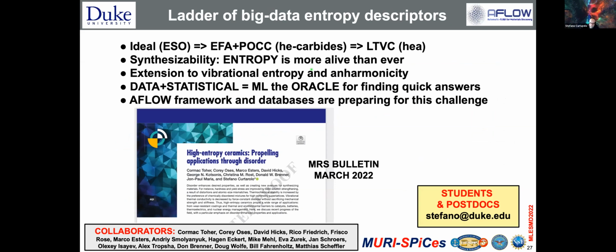Anyway, let me summarize. Disordered systems. We have embraced disordered systems since several years ago because we believe that disorder is unavoidable. We want more things, so disorder is going to kick in. To understand synthesizability when this disorder kicks in, it's all about entropy, because entropy gives you the latent heat. And the latent heat is important for nucleation. And you will find also, for instance, in advanced manufacturing, 3D printing, when you have adiabatic zapping or non-adiabatic zapping, that nucleation depends on how the latent heat can go around and can change the way the nucleation happens.